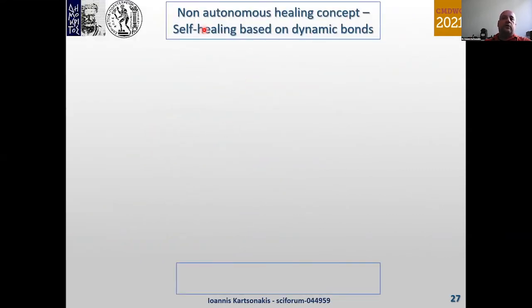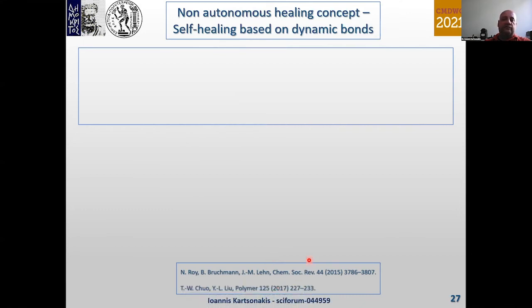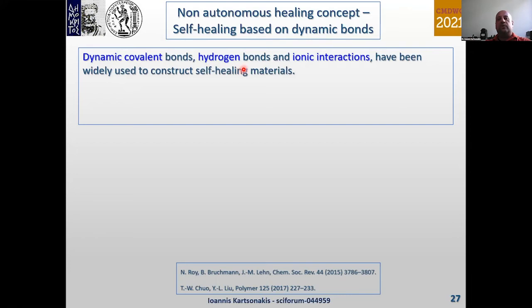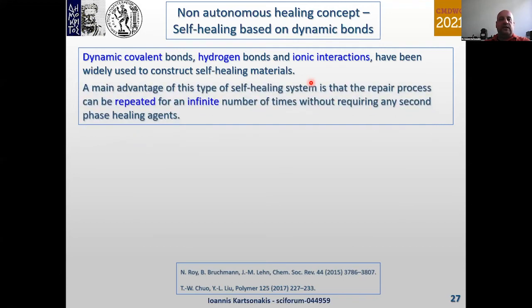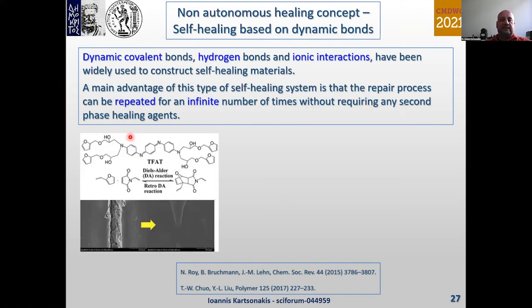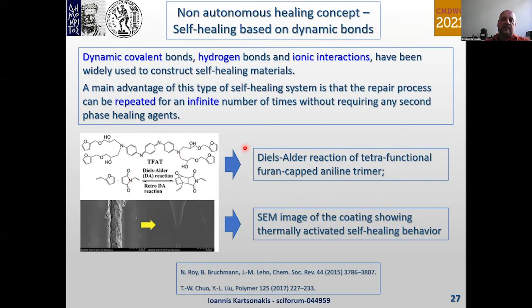Also, based on dynamic bonds of non-autonomous self-healing coatings, from the work of Roy 2015 and Chuo 2017, we can see that dynamic covalent bonds, hydrogen bonds, and ionic interactions have been widely used to construct self-healing coatings. The main advantage of this type of system is that the repair process can be repeated an infinite number of times without requiring any second phase healing agents. We can see here, for example, the Diels-Alder reaction of this trimer, and after the reaction the crack was sealed.